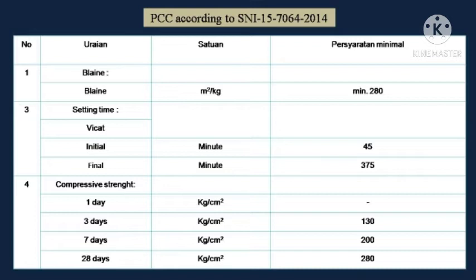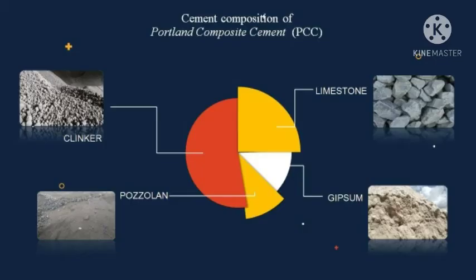And the last is 28 days, which has a minimum requirement of 280 kilograms per square centimeter. As for the composition of PCC cement, it consists of four materials, namely clinker, pozzolan, limestone, and gypsum. Clinker is the main raw material for the manufacture of cement, which is produced from various calcium silicates. Pozzolan is a material that contains alumina and silica and functions as a compressive strength enhancer.